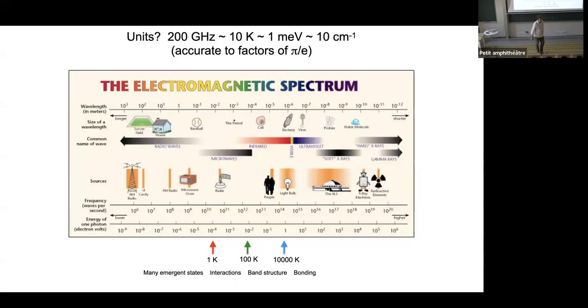But my question was more experimental. Yeah, okay. Experimentally, the answer is yes. People in strontium ruthenate have seen omega-squared scattering. I don't know of examples where people have seen, say, T^5 scattering from electrons coupling to acoustic phonons, but that would be interesting. That needs very low temperature, maybe high resolution. Okay, thank you.